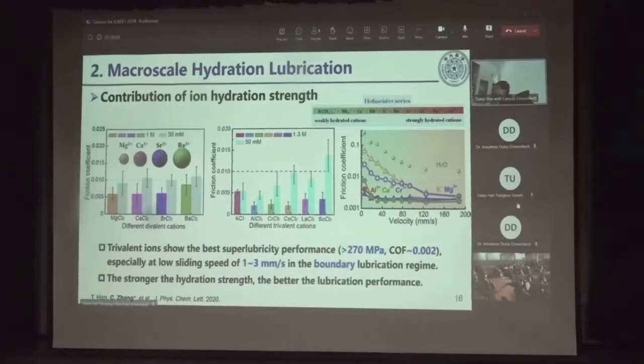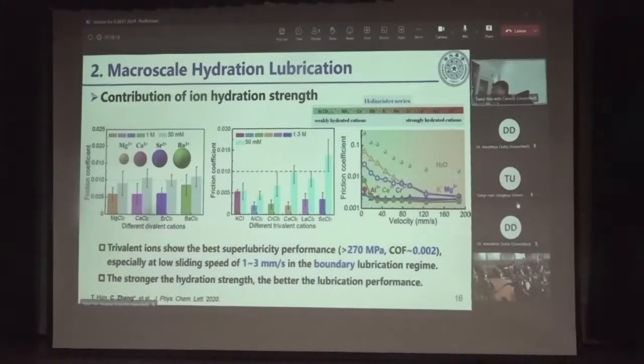The interesting thing is that for trivalent compounds, the super low friction coefficient can also be obtained at a very low sliding speed. A low sliding speed means almost no liquid film between the surfaces. Only the hydration layers consisting of the hydrated compounds support the applied load. So the trivalent compounds show the best superlubricity performance. Then we can conclude that the stronger the hydration strength, the better the lubrication performance.